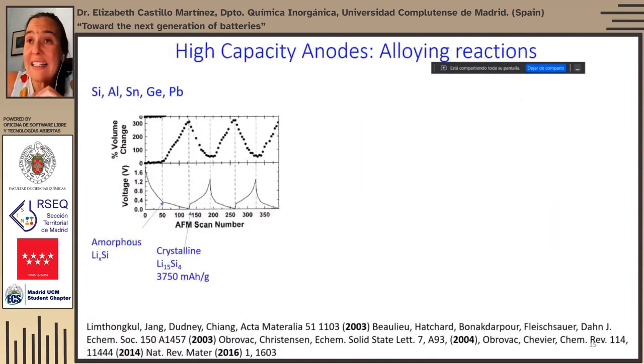On the anode side, there have been lots of reports as well on trying to use high-capacity anodes. Remember that graphite has about 370 milliamp hours per gram based on the insertion of 1 lithium ion per 6 carbon atoms. But when lithium reacts with group 14 elements like silicon, aluminum, tin, germanium, lead, it can react through alloying reactions, which can give much higher capacities.